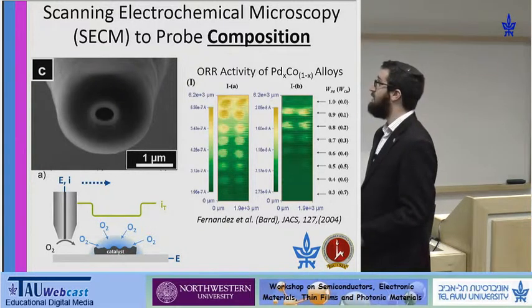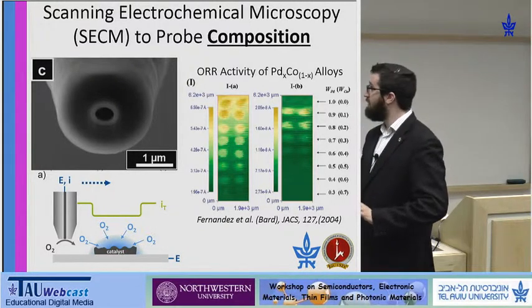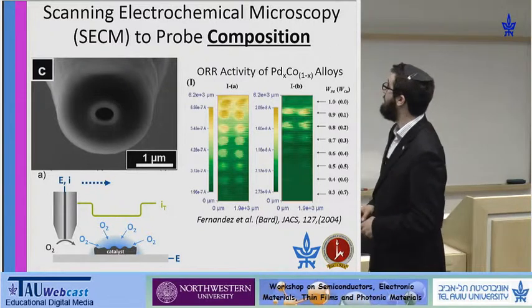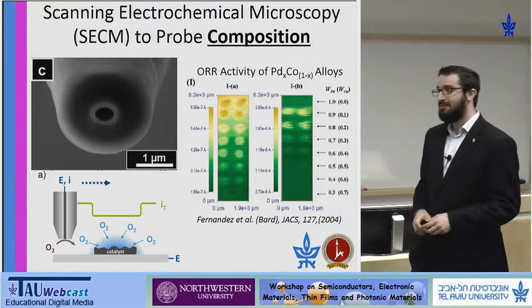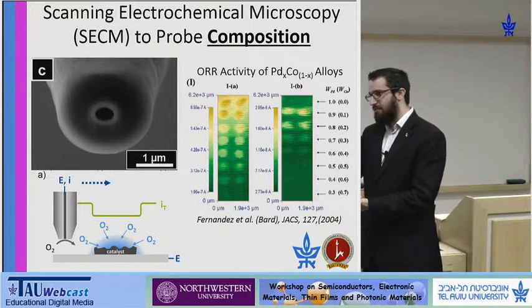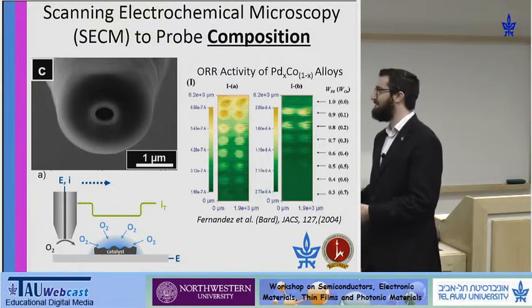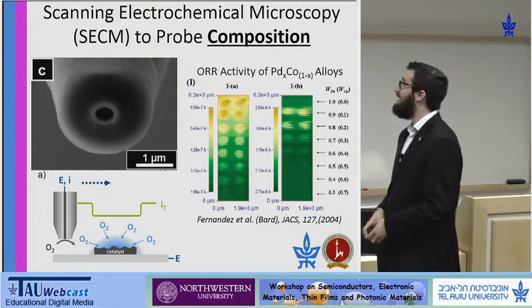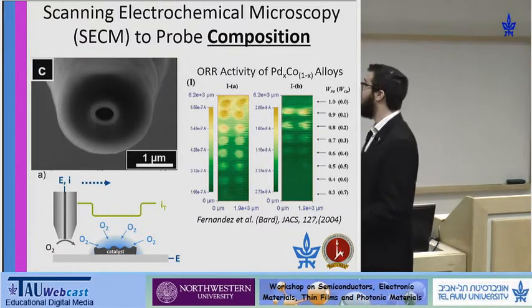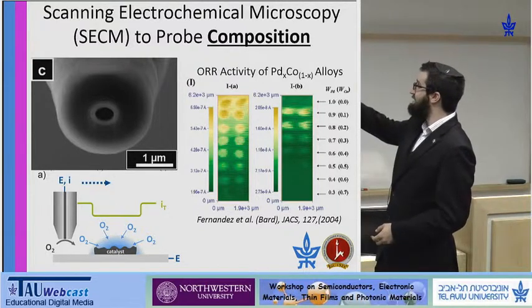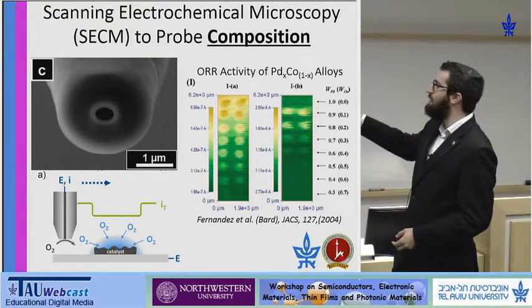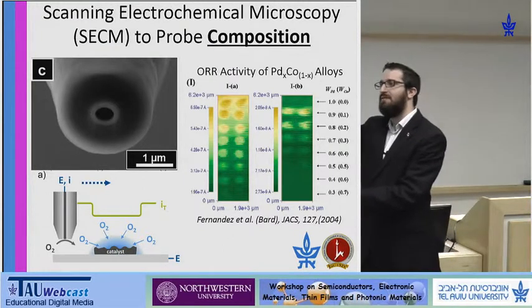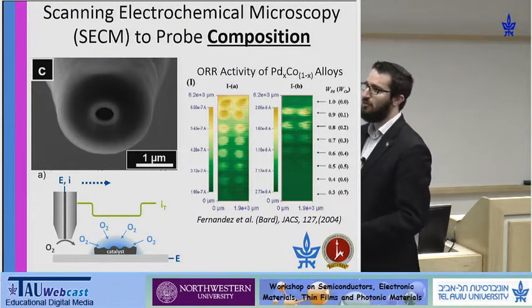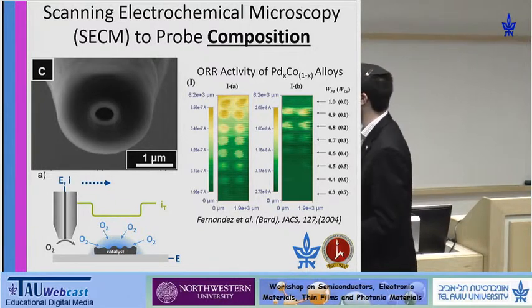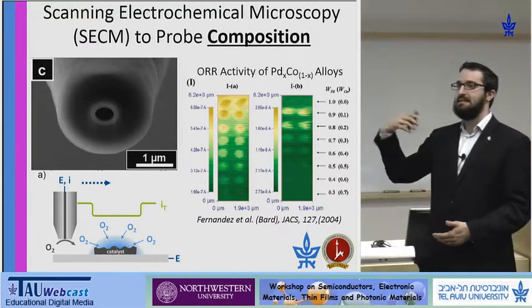for catalysis work. So one other technique I'd like to speak about before I finish is what's called scanning electrochemical microscopy, which is a way similar to STM where you can use a probe in order to look at local catalytic activity, particularly for oxygen reduction activity. And what people have done in the past very nicely is to make these dots of different compositions. They're making alloys, and they can scan the tip over the different compositions as a way of high-throughput screening for alloys in electrocatalysis. What we want to do is we want to take this a step further.